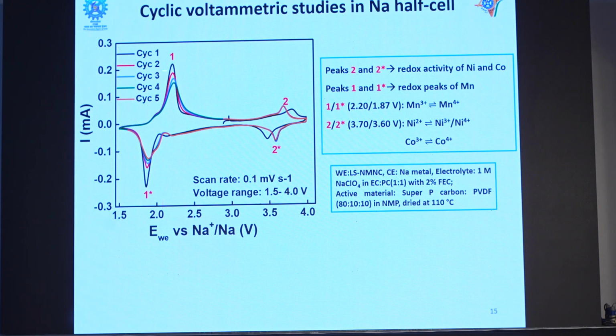So the upper part, when it is a positive current, it is oxidation, and when it is a negative current, it is a reduction. And then when we charge the battery again, the 1 star, that is the manganese electrochemical activity, could be reversible. And then we are again getting the 2 star electrochemical activity corresponding to nickel and cobalt oxidation. And how can we make sure that it is cobalt or it is nickel? So in principle, we can calculate a little bit, but if you want to see it with your own eyes, you can use operando techniques.